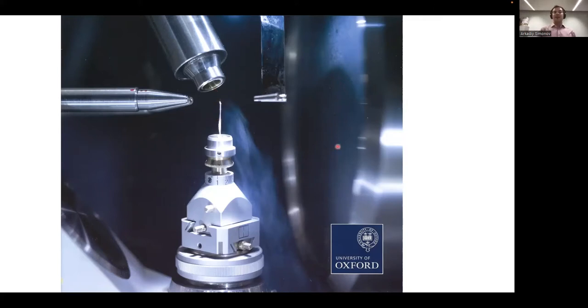Then there are lots of other things. You'll have a big detector. These days, they're quite large detectors, on the right-hand side, out of focus. There's also a beam stop, so that the primary beam doesn't hit the detector directly, because they are very sensitive. They wouldn't like it that much. And also, we're going to be changing the temperature. Organic molecules are not always stable. If you cool them down, they're going to be more stable. So we usually use a flow of cold nitrogen coming through here to get them to around 100 Kelvin.